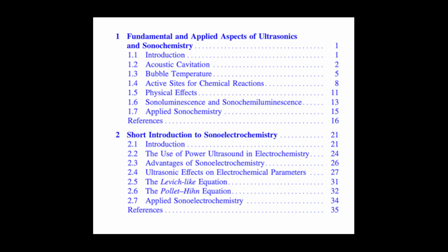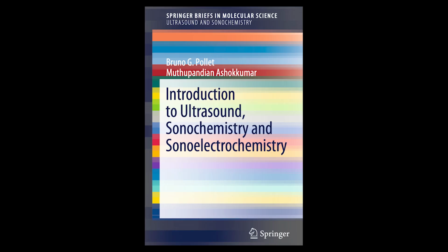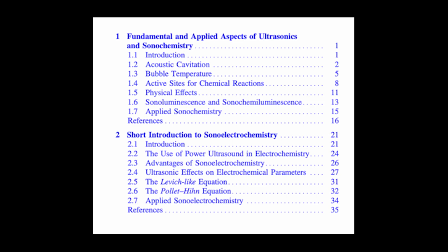Continuous, aggressive cleaning of the electrode surface. Those microjets scour away any passivating films, reaction byproducts, or general gunk that might build up and block the active sites on the electrode. This is huge for preventing electrode fouling. Fouling is a massive headache in industrial electrochemistry, right? Electrodes just stop working over time. A massive headache. SEC can keep surfaces clean and active for much longer.